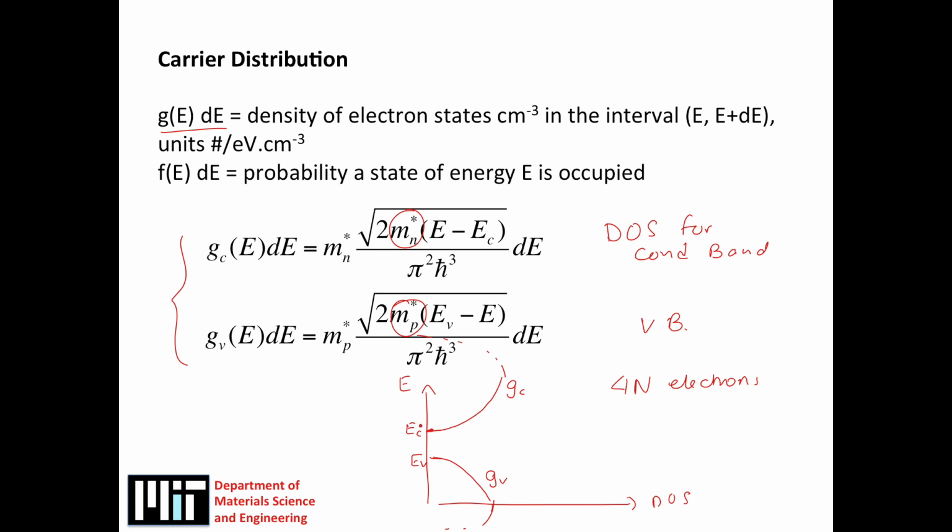But from the point of view of the vicinity of the band gap, near E_G, they are parabolic, and it doesn't really matter too much what happens way up here or way down here, because down here is always fully occupied and way up here is never occupied. So from the point of view of doing calculations, the assumption that these densities of states are parabolic is pretty good. But when you do integrations and so on, you have to remember that they don't actually go on forever. Otherwise, we'd be able to populate them with an infinite number of electrons and holes.